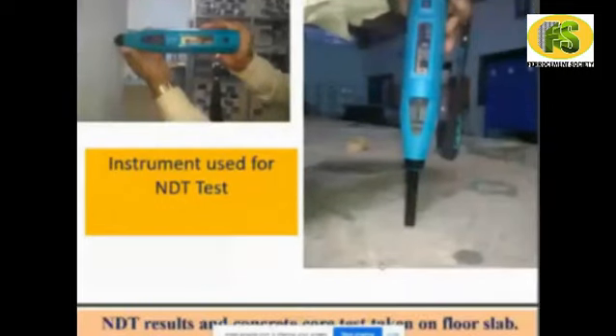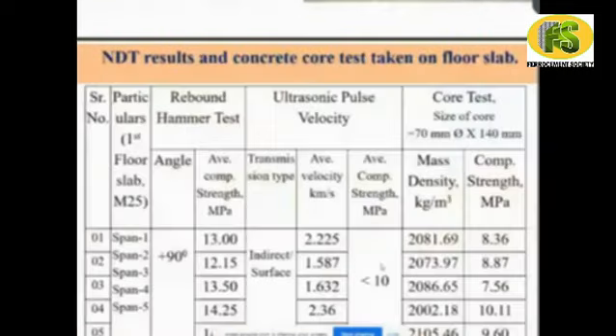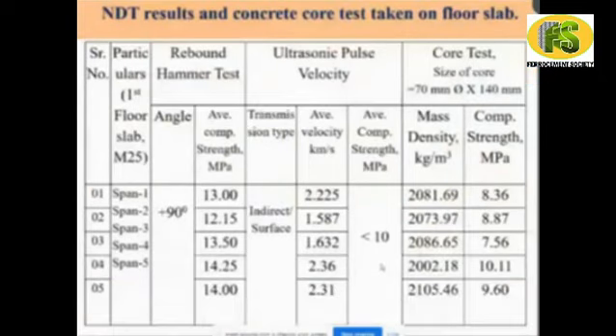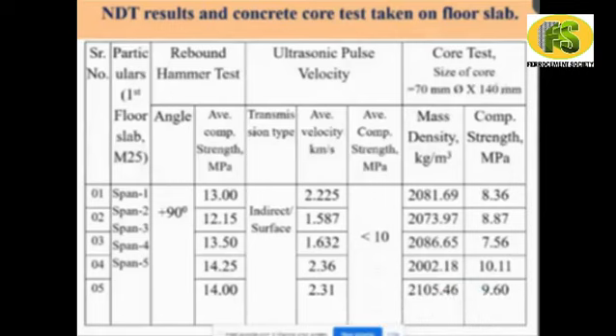So this is the NDT result of the concrete core test taken on the floor slab. Here it is observed: Rebound Hammer, ultrasonic concrete tester, and the core test. We have taken the core. The diameter of the core is 70 mm and the length is 140 mm. And here also we were really surprised. The depth of the slab is 160 mm, but in the total core we took, the thickness of the slab is 140.